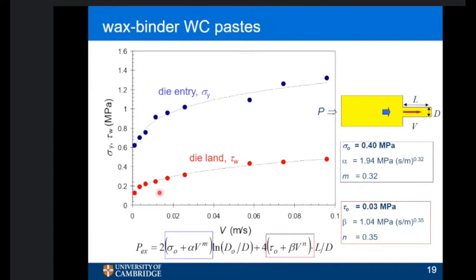The other plot we got here in the red is the die-land behavior. That gives us the wall shear stress, and we're talking about 0.1 to 0.4 megapascals. So that's quite a lot of work to make it move along a die-land. So this gives us a way of characterizing the materials. If we change the formulation, we can find out what these numbers are, and then we can put these numbers into simulations, whether it's a solid mechanics or a soil mechanics sort of code, in order to model what we'll go and find out the pressures.